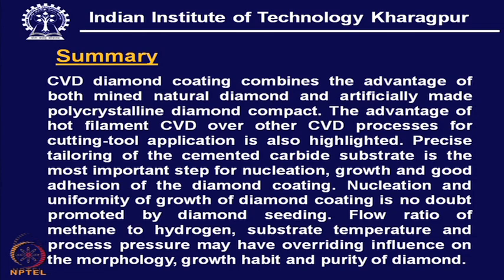Nucleation and uniformity of growth of the diamond coating is no doubt promoted by diamond seeding. So here we find two issues: one is to accelerate the process and to act like a catalyzer, for which diamond seeding is one of the important steps. Flow ratio of methane to hydrogen, substrate temperature and process pressure may also have an overriding influence on the morphology, growth habit and purity of the diamond. But what is important here is, finally, a well adherent diamond with fine structure and a process capability which can facilitate deposition of this diamond coating over any complex geometry. That will decide how useful this process would be in practical application.